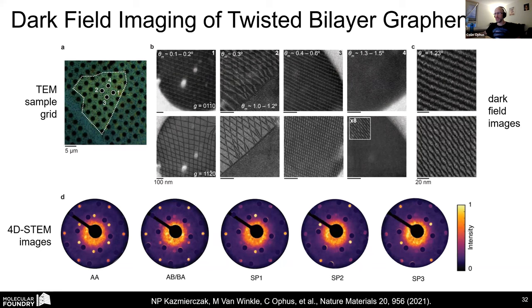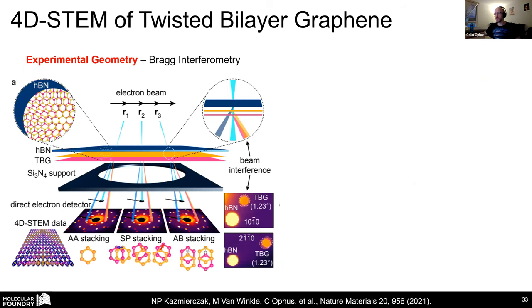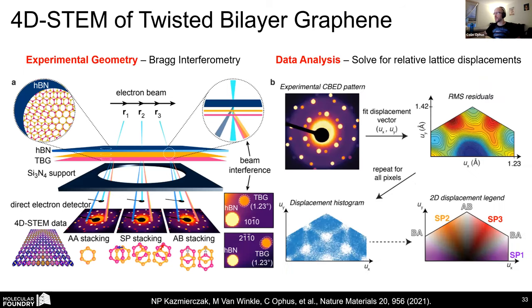But if you look at the innermost and outer or second ring of the graphene diffraction spots here, you can locally measure whether you have AA stacking, AB stacking, or one of the saddle point edge stackings. And these sort of unique fingerprints here can give you the local stacking. And if you do this over a large sheet of this material and then pull out all of those CBED patterns, the convergent beam electron diffraction patterns, we came up with a mathematical way to transform this into a displacement map to sort of ensure local continuity over the two lattices.